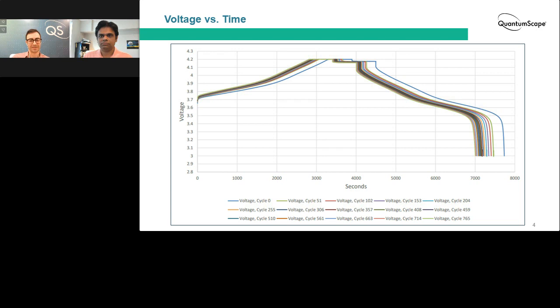And then the other cycles that you see in other colors laid on top of that are from roughly every 50 cycles throughout the rest of the cycling test. And so you can see that the performance cycle to cycle is really quite stable, that the voltage is increasing smoothly. It's just a very typical constant current, constant voltage test. There's no pulses or nothing else funny going on.